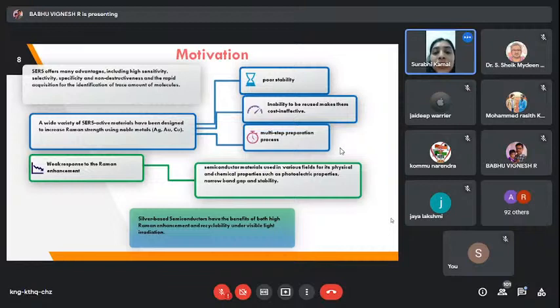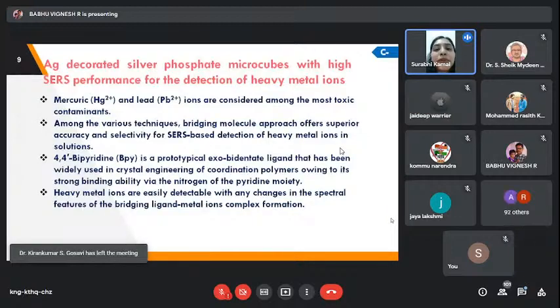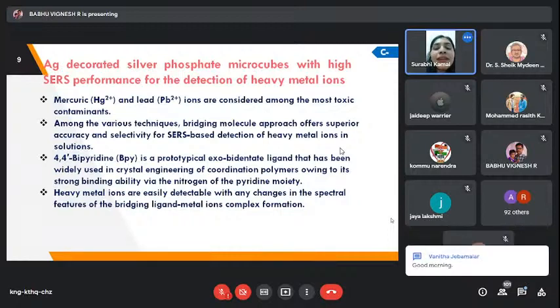So what I did was synthesize a silver-based semiconductor to have the benefit of both worlds. So I just made silver-based materials. So this is my PhD motive. We are now talking about one of my papers, which is silver decorated silver phosphate microcubes with a high SERS performance for detection of heavy metals. As you all know, mercury and lead are considered among the most toxic contaminants, and there are various methods to detect mercury as well as other heavy metals and toxic materials. And one of the beautiful things about SERS is you only need a small amount of material, and you can detect up to the molecular level of 10 to the power of minus 9 or 10, the nanomolar level. You can detect the particles.